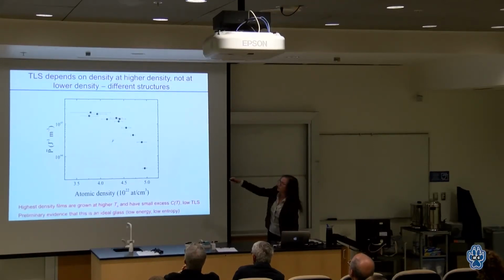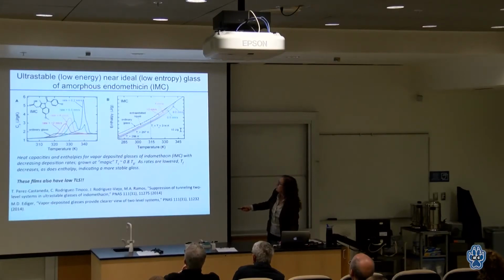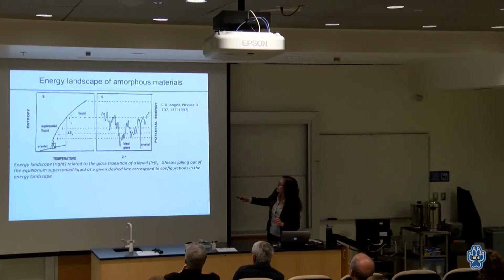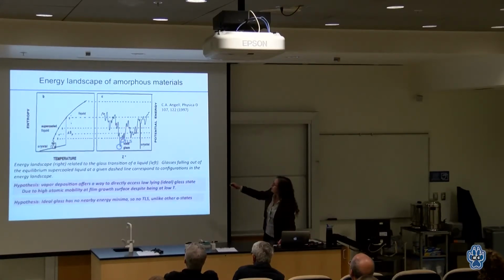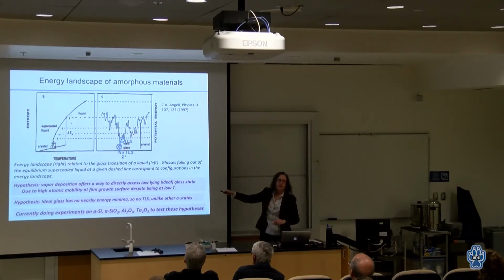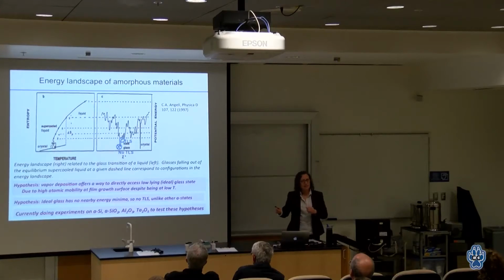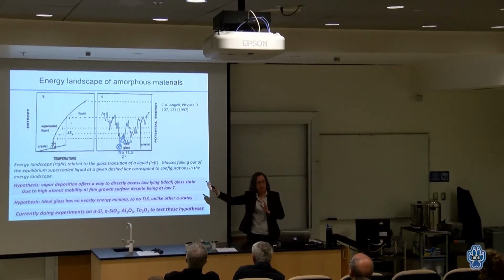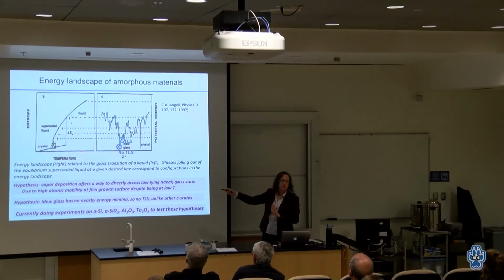We'll skip past this. We have a bunch of data points of this, and so we've shown that it depends on density. The thing I want to say, getting back to this plot, is that the ideal glass state has no TLS. That lowermost state has no low-lying nearby states, so there are no tunneling states. So in a big picture way, we've now connected a high temperature property, how something comes through the glass transition, and this ideal glass, with this concept of TLS.